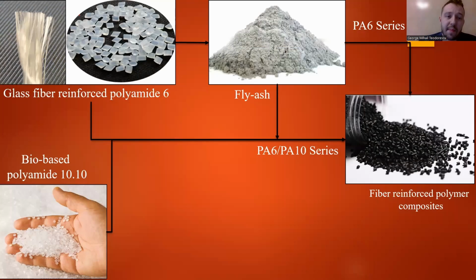We used polyamide 6 reinforced with 30% glass fiber and bio-based polyamide 1010 as the polymer matrix. We conducted 2 series of experiments. One where we mix the glass fiber reinforced polyamide 6 directly with treated ash, and this series is marked as the PA6 series. And the other one where we mixed the glass fiber reinforced polyamide 6 with polyamide 1010 and the treated fly ash. And this was marked as the PA6 PA10 series.